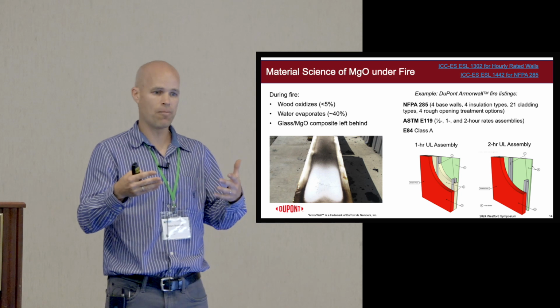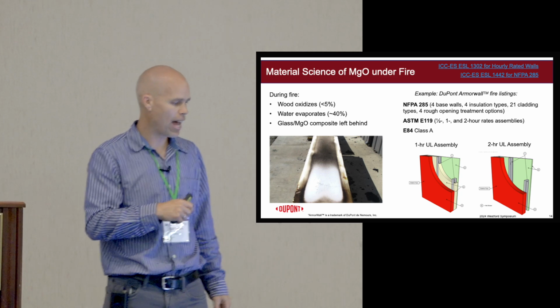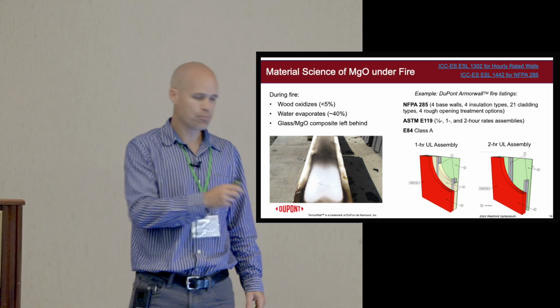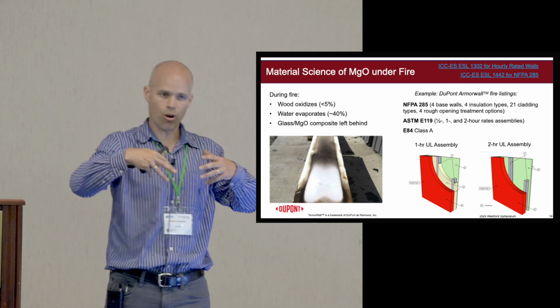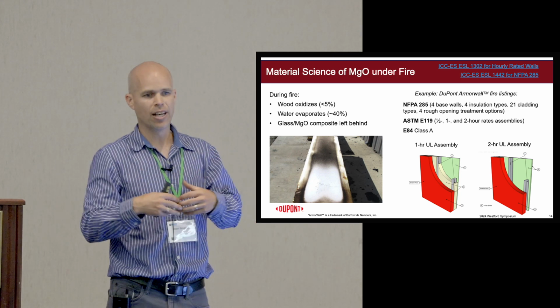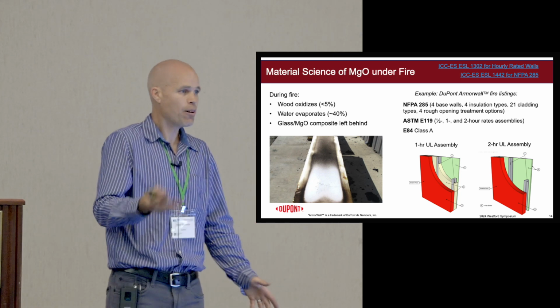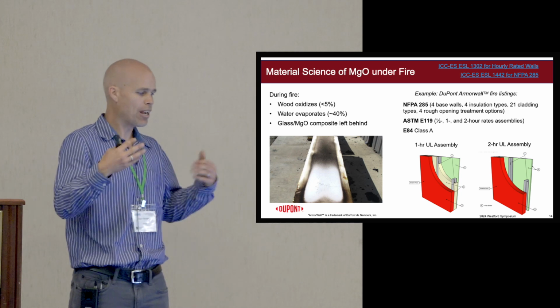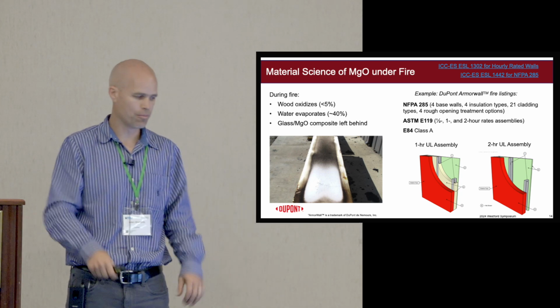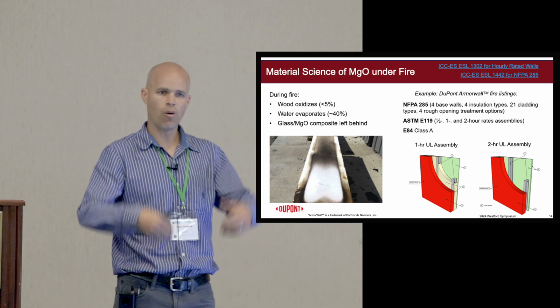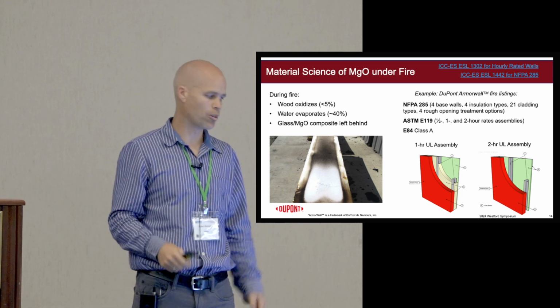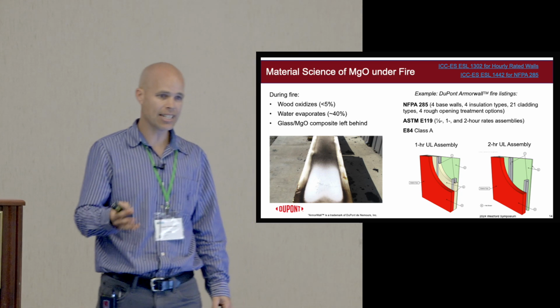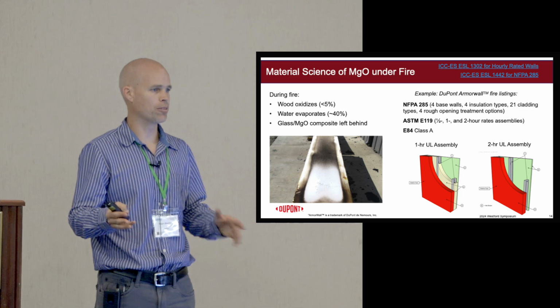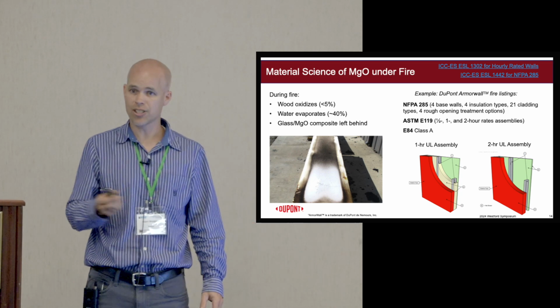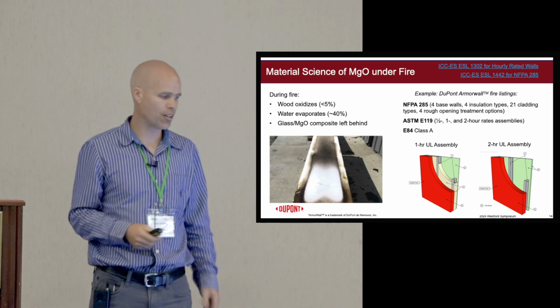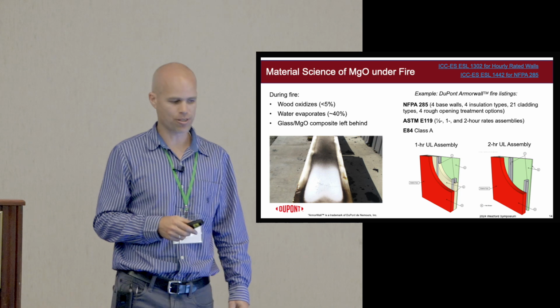It does generate a small amount of heat, but that's counteracted by the fact that this board, because of the water that's incorporated into the crystal, and the cement, plus other water that's in there, it's about 40% water. So when it starts to get hot during one of these tests, a lot of that water is evaporating, keeping the material cool, and what's left behind is 100% non-combustible. Magnesium oxide as a raw material, or mineral, and the glass fibers.